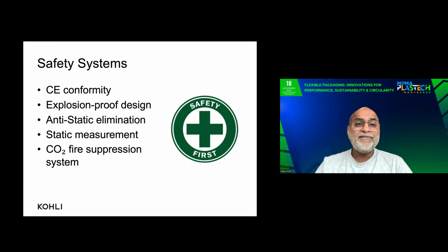Safety cannot be ignored anywhere in the world. The equipment has to be CE conformity, explosion-proof design. Static is a very big challenge today because as the films are getting thinner, production speeds are becoming faster. This is a big challenge in a lot of machines. So the equipment has to be ready for anti-static elimination. And we at Kohli believe very strongly that just eliminating static is not enough. Because over time, 1 year, 1.5 years, the static eliminating bars accumulate dust and the power reduces, which you may not be aware of.